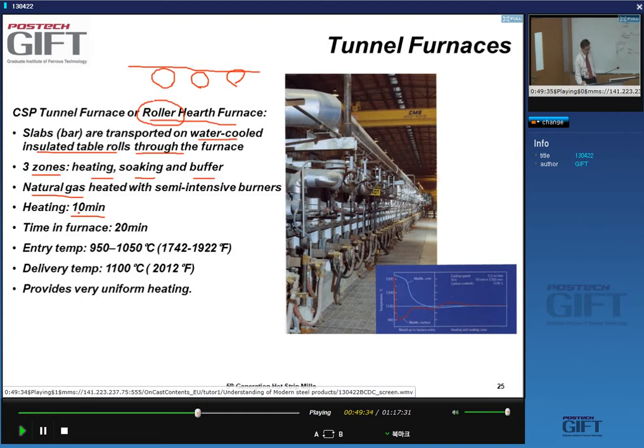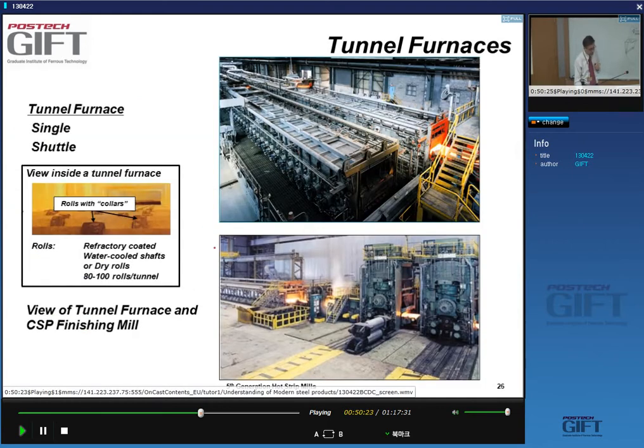10 minutes to heat up, and the total time in the furnace is typically 20 minutes. The temperature at which the material comes out of the caster and goes into the furnace is in the range of 950 to 1050, and you deliver typically the material at 1100 degrees C. And because you're basically heating the slab from all directions, the uniformity of heating is quite good. So this is definitely a metallurgical positive point of this CSP technology, this homogeneous heating.